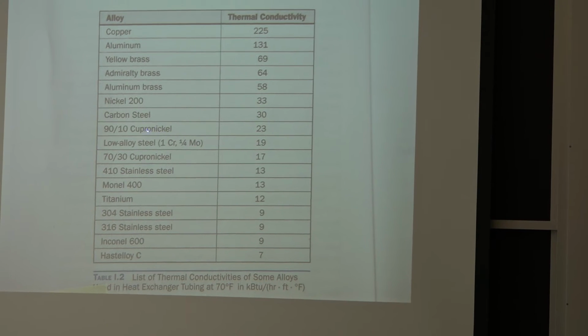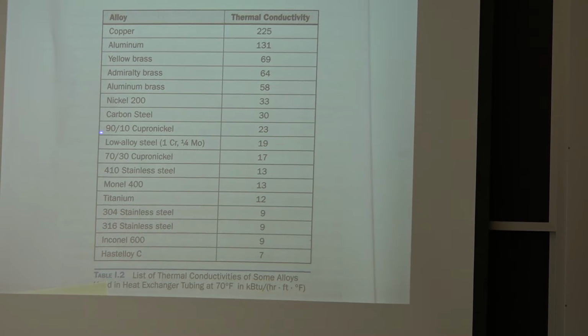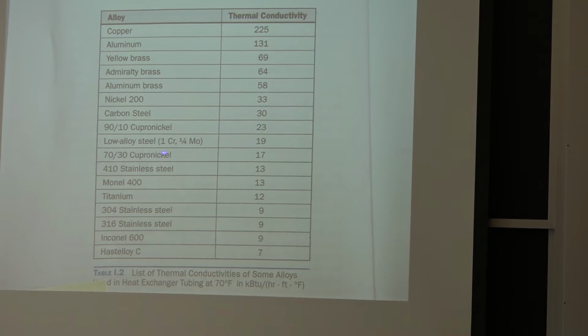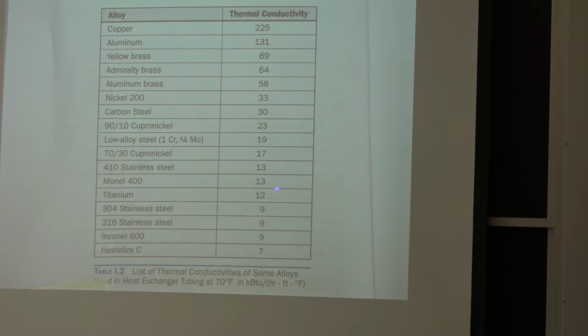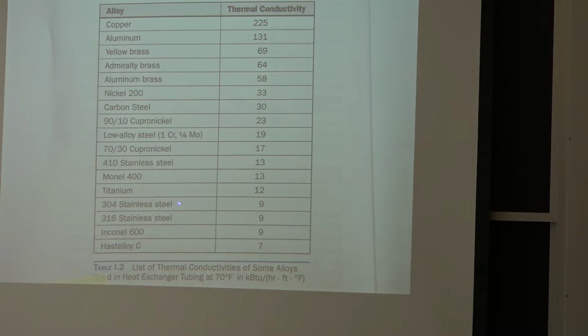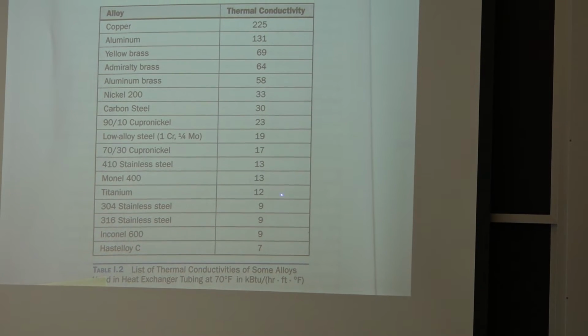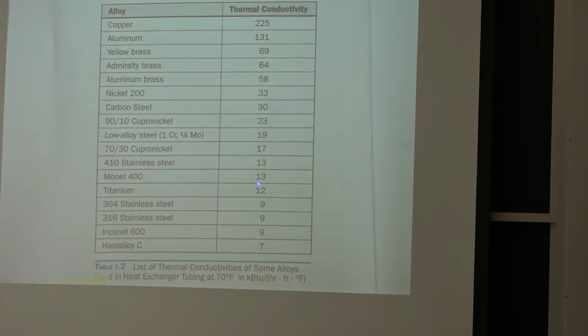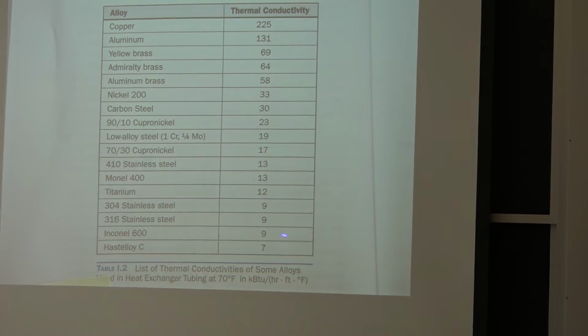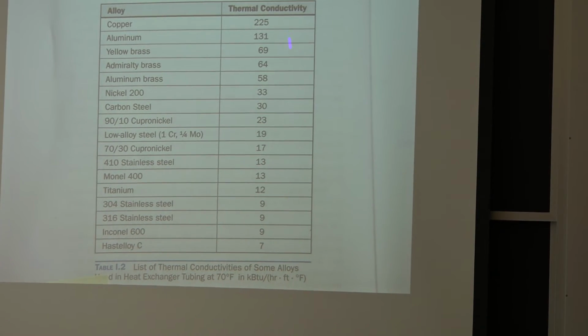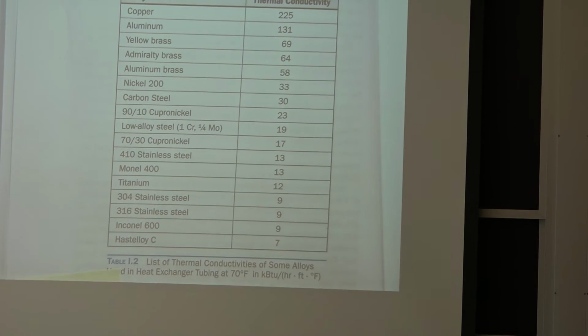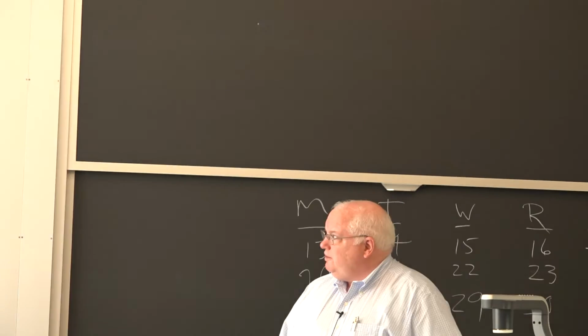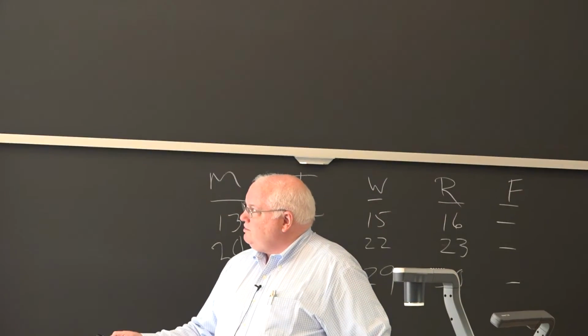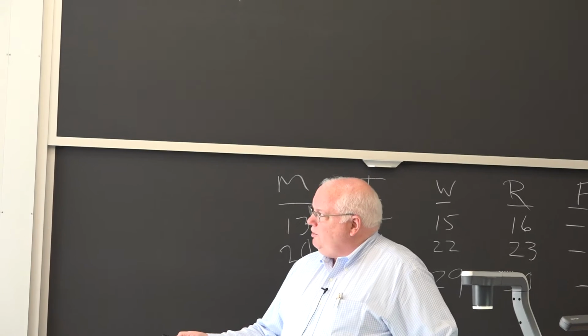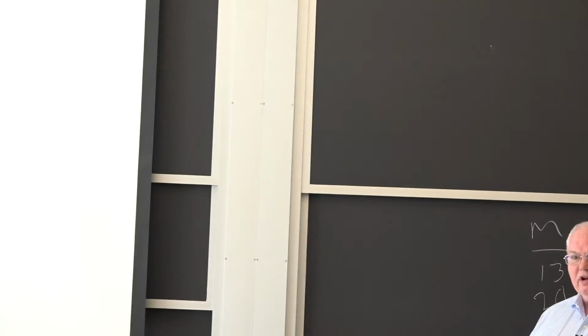Of course, carbon steel, we all know it rusts. And then the Navy likes to use cupro nickel, okay? Cupro nickels, although they tend to like to use the 70-30s or the Monels, which are 30-70 cupro nickel, if you will. And now you're really biting the dust. You can use stainless steel, it tends to pit. Titanium is better than stainless, and it's got fantastic corrosion resistance, we'll see. And if you have to go to really high temperatures, not well beyond water, you can use some of the nickel-based alloys. But I mean, there's a whole host of materials. And if you're talking about condenser tubes or boiler tubes, these are the types of materials you use. And of course, if you're talking nuclear reactors, boiling water reactors, typically used in stainless steels, you're talking pressurized water reactors, we're getting into the Inconels, okay? Just has to do with the operating temperatures and conditions.